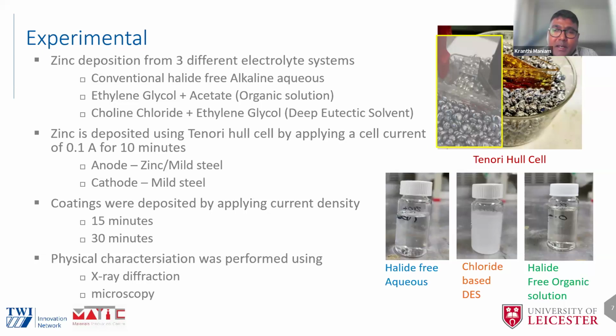The industrially used plating cell is the Hull cell, which is 267 ml. Since we are dealing with organic solutions which are expensive, we thought to go with a miniature cell known as the Tenori Hull cell, which mimics the industrial plating cell. That is used to optimize the current densities and make a comparison amongst the three electrolytes. That was the first innovative thought we had, and we applied a cell current of 0.1 amperes, and we computed the current densities along the panel.